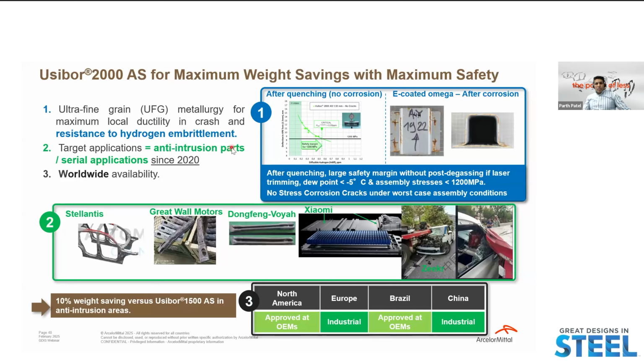In Usibor 2000, over the last 2 to 3 years of experiments with hot stampers, we haven't seen more than about 0.25 ppm. We always recommend controlling the dew point, but our message is that if you bend the material in a 4-point bending test at 1200 MPa strength, even with 0.5 or 0.55 ppm diffusible hydrogen concentrated in the material, you're still above the limit and good, because assembly stresses are less than 1200 MPa.